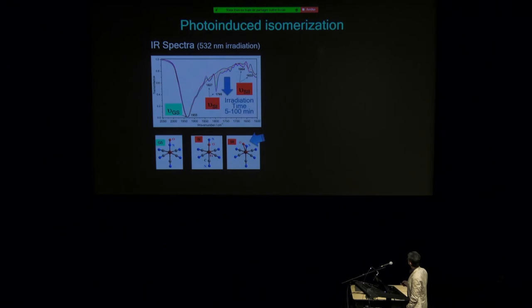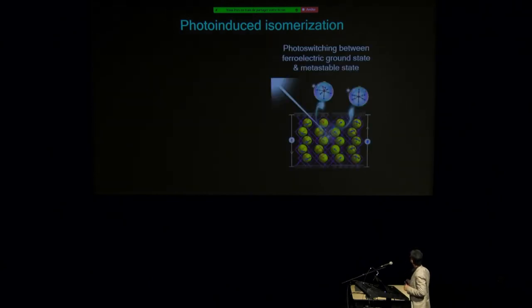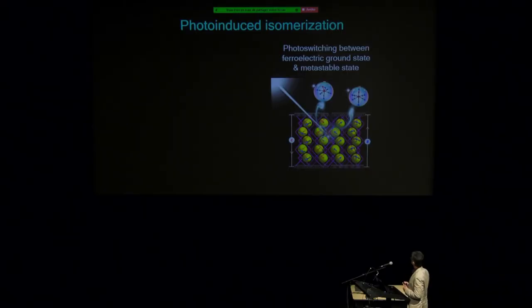What we have here is a ground state, which is represented by this normal bond, nitrogen to iron, and two metastable states: this one here is oxygen bound to iron, and that one makes a sort of ring. And so, with light, you can actually change, and that's basically what this picture wants to show, you can photoswitch from the ferroelectric ground state to two different metastable states. Hopefully, this will also be able to switch the ferroelectricity of this system. We have not done experiments yet of low temperature measurement of ferroelectricity upon light irradiation, but we've done them separately. That's the next step.